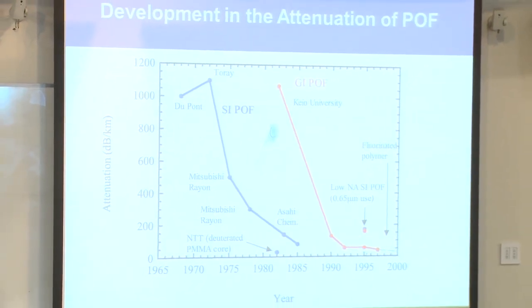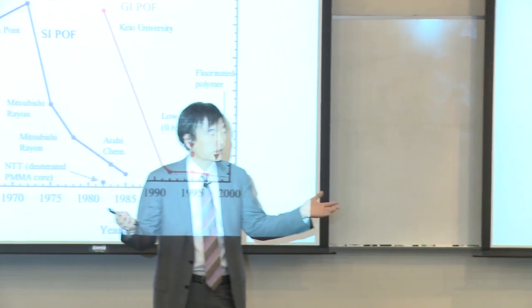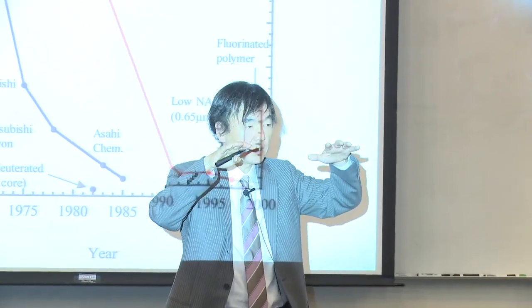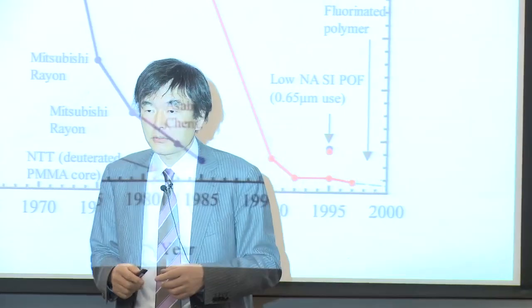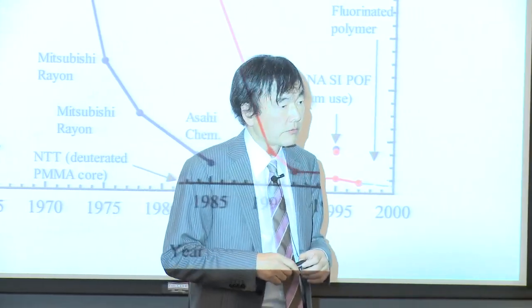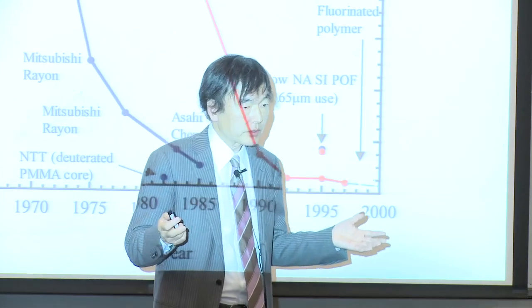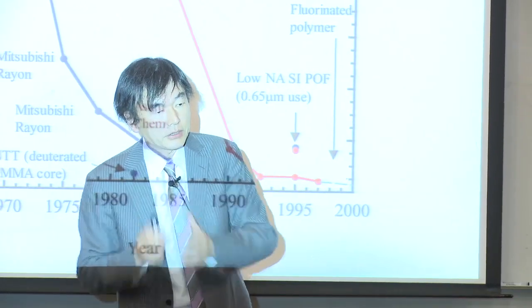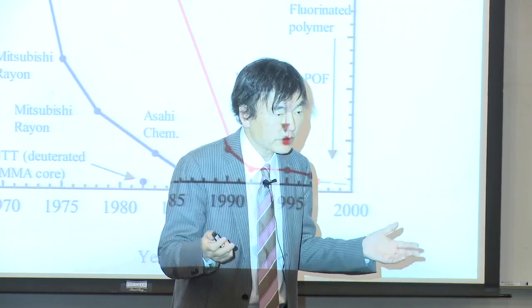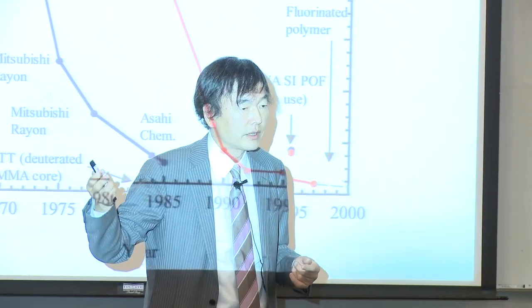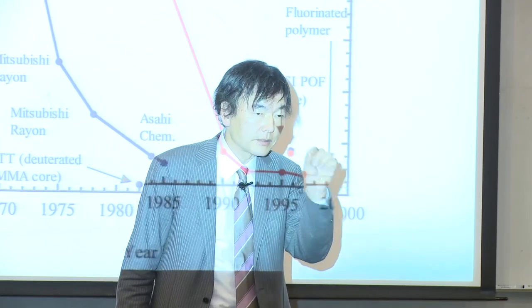But people said that copolymerization is much better than adding dopant, because adding dopant, due to the plasticizer effect, lowers the glass transition temperature and thermal stability. Actually, after that, spending 20 years, graded index plastic optical fiber has now been commercially available from, for example, Asahi Glass Corporation, one of the biggest chemical companies in Japan. Now this fiber is stable from minus 25 degrees centigrade to 80 or 90 degrees centigrade.